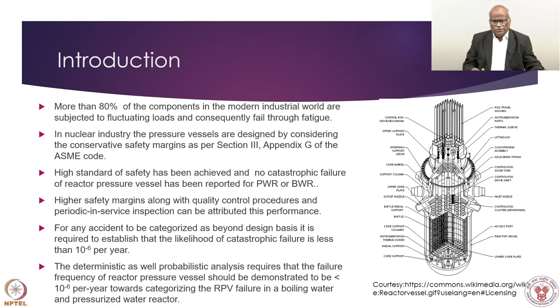We know that in passive structures, the major failure mode is fatigue. It could be thermal fatigue or mechanical fatigue. And 80% of components in industries, like bridges and structures, fail even if they are not touching the maximum permissible allowed stress; cyclic loading has its own mechanism and the components fail. Of course, there are codes and guides, and for pressure vessels especially we have ASME Section 3, Appendix G, and the reactor pressure vessels are designed according to this code. But the final criterion is that it should be demonstrated that their failure rate will be 10 to the power minus 6 or less, so that their failure can be considered beyond design basis.